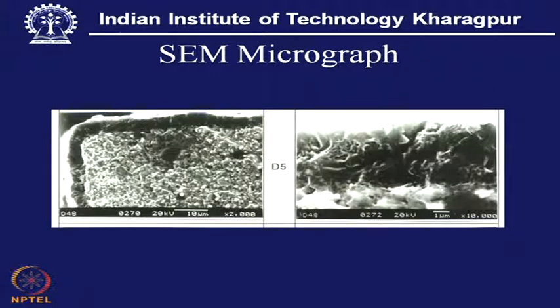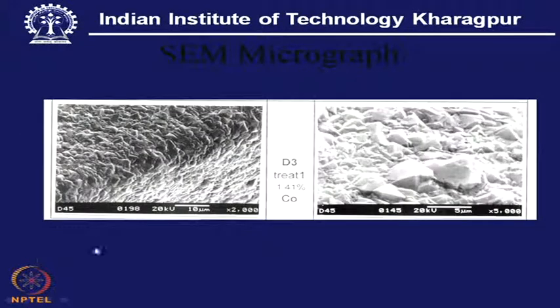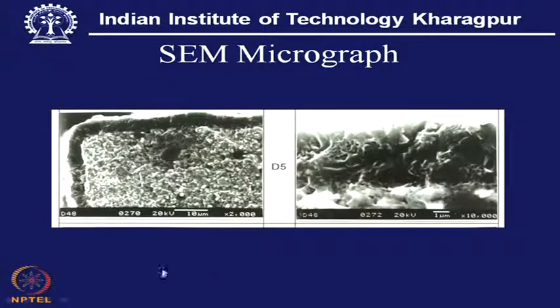Now, what we see, now we go to the cross section, that means it is a fractograph. So, this is also the SEM which gives us that picture. So, this is important in that this picture gives us a clear idea about the coating process or the coating technology. That means the coating process itself is capable of not just coating a flat surface, but two surfaces, that means one face and flank, two surfaces at right angle, and this is the edge. This is the edge, that means if we go to the first slide, this is the edge. So, if we make a cross section here by fracturing, then we get this picture.